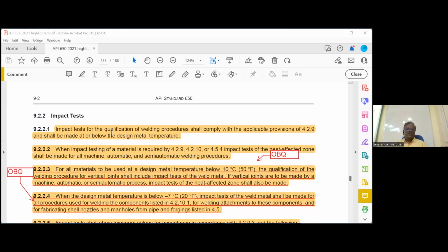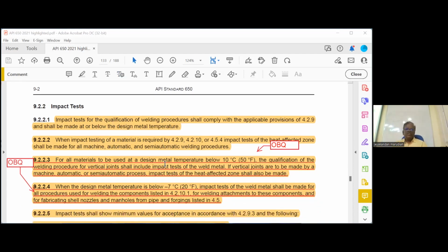Okay, this is the next one. For all material to be used at a design temperature below 50 degrees Fahrenheit, the qualification of the welding procedure for vertical joints shall include impact test, irrespective of materials. See, generally, in chapter 4, how do we find out? We have to see the group number. Then we have to use the equation. If you want to use below this, then impact test is required. If you want to use above this, impact test is not required. That is separate. That is for material.